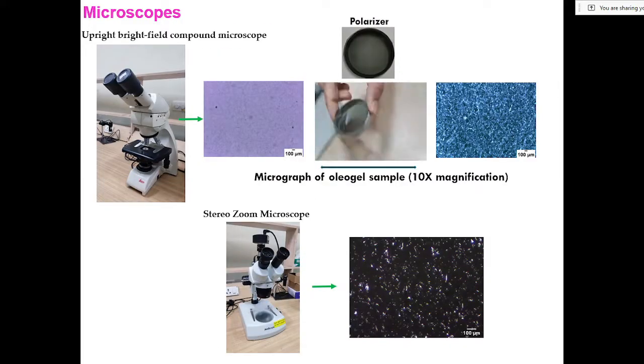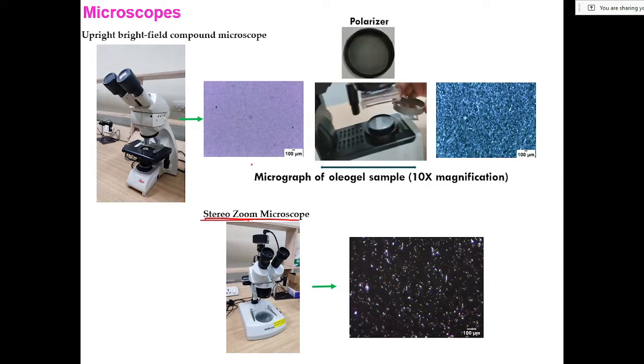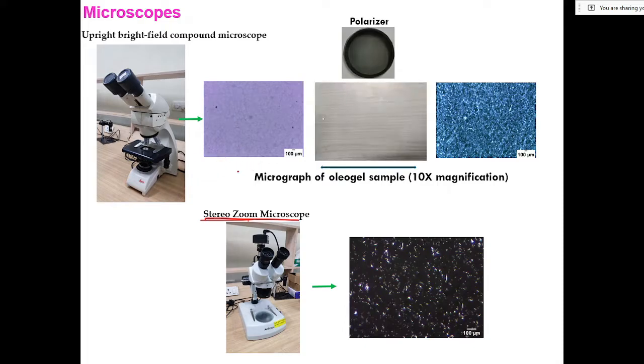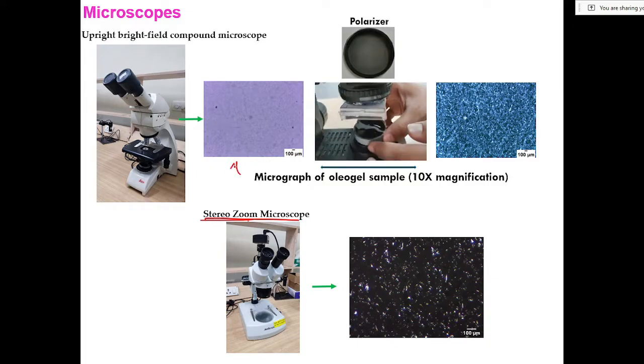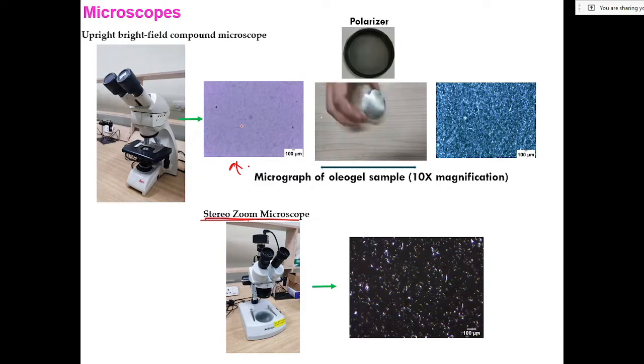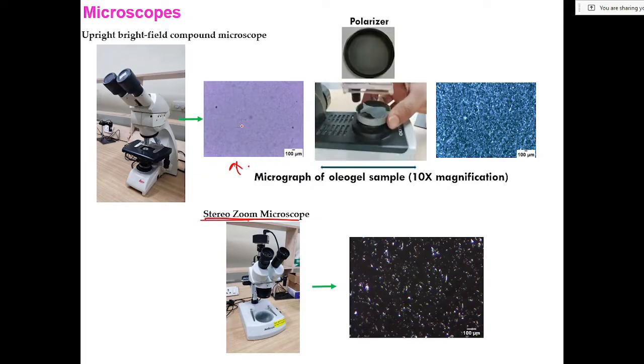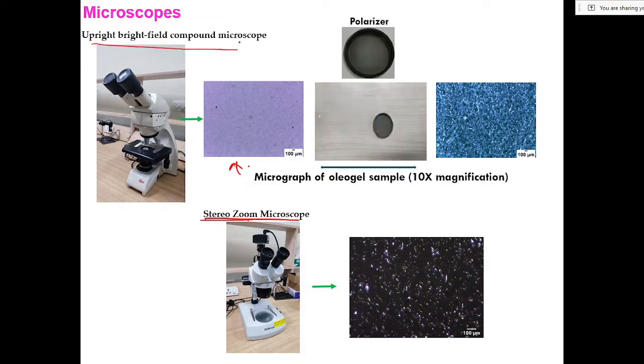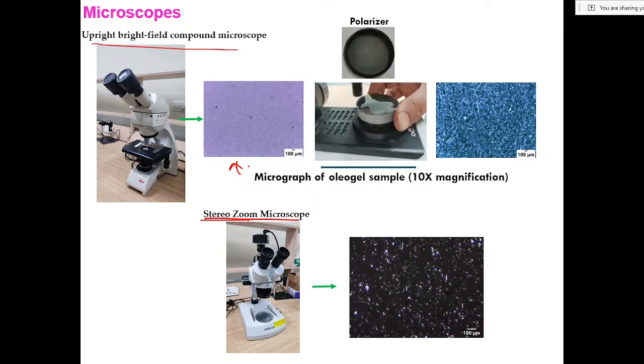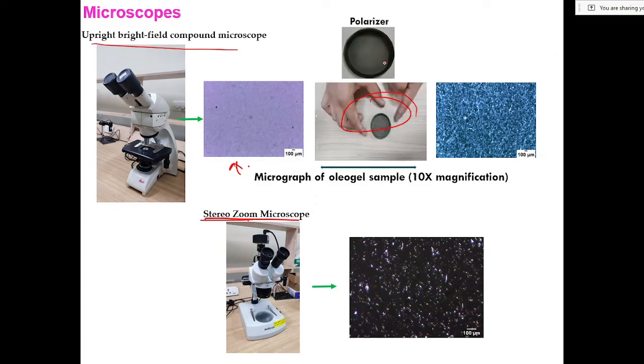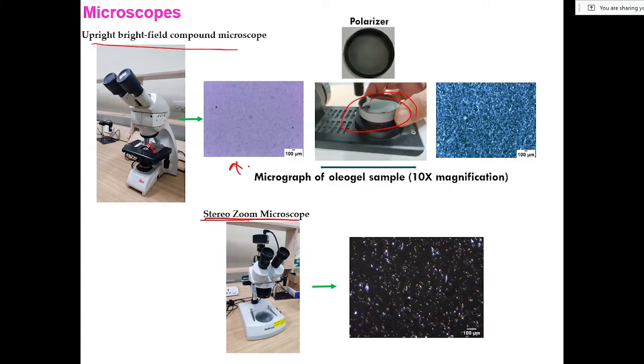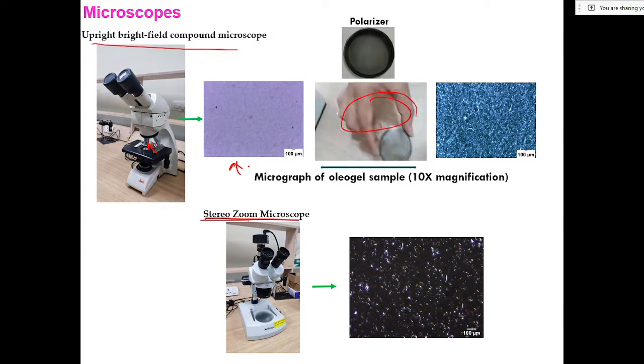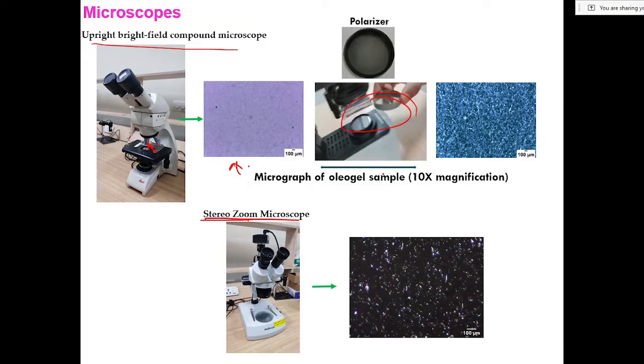so then we went for the microscopic analysis. Initially we did it with the stereo zoom microscope, then we had a bright field microscope. We analyzed the micrographs using the bright field microscope. However, if you see the bright field micrographs, many a time they do not give you very good information. So we converted our upright bright field compound microscope into a polarizing microscope, and this is what we did. We used a polarizer, and to the eyepiece lens, the objective lens, we added this polarizer over here, and we converted the upright bright field compound microscope into a polarizing microscope.